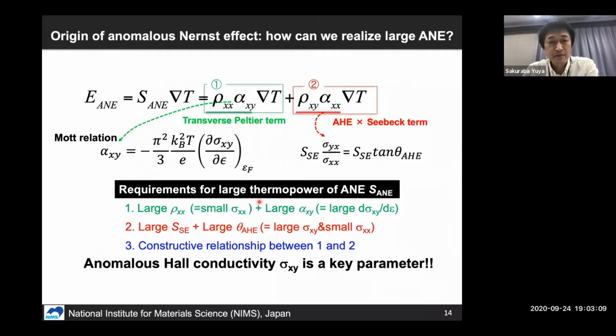So this linear response equation gives us the tips to explore materials having a large anomalous Nernst effect. As you can see, the thermopower of the anomalous Nernst effect can be divided into these two components. The first term is a product of resistivity and the off-diagonal part of the thermoelectric tensor. And the second term is a product of rho xy, the anomalous Hall resistivity, and the diagonal part of the thermoelectric tensor.